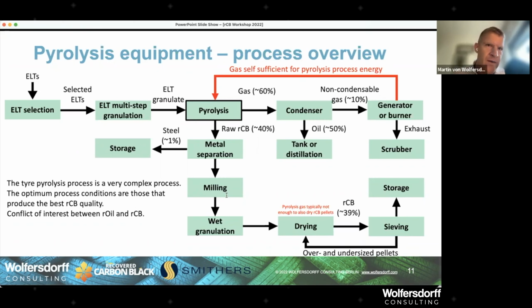Of course, it is a problem when the end-of-life tire feedstock already has recovered carbon black with a certain ash content. And then we would enrich the inorganic or ash content in the recovered carbon black. At that point, we really need ash leaching or ash reduction technologies. Right now, to reduce the ash, we have the leisure of choosing a feedstock or mixing a feedstock such that the ash is not more than a given amount. Typically, and I will get to that a bit later on as well, people are now targeting less than 20% ash content. And the reason for that, I will tell you a little bit later in the workshop. But you could do for that, even in Europe, you could mix, let's say, 75% car tires and 25% bus and truck tires, and you will get to that kind of level. I hope that has replied the question.